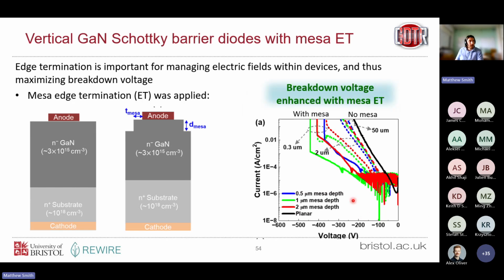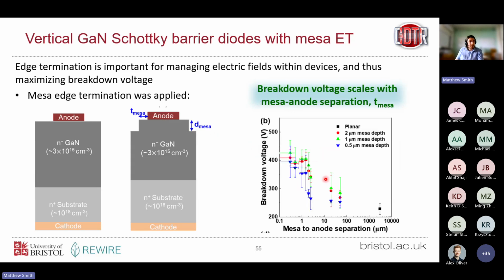semiconductor properties. And here we can see the range of values that we get when we apply MESA edge termination in terms of our breakdown voltage. So this black line here is our planar device, so this one over here. So we apply voltage in reverse bias, it's breaking down around 200 volts. But when we apply this MESA edge termination with these different T MESA and D MESA values, we can see we definitely increase our breakdown voltage, and how much we increase it depends on what the dimensions of these numbers are. So this is summarizing that plot.